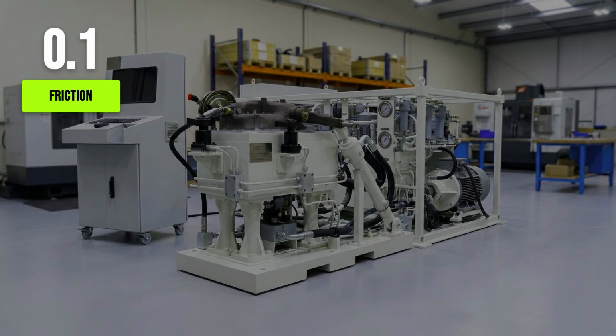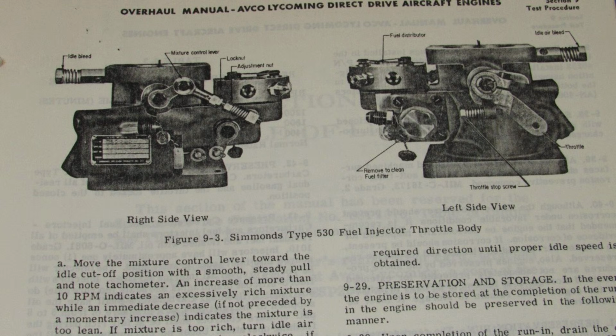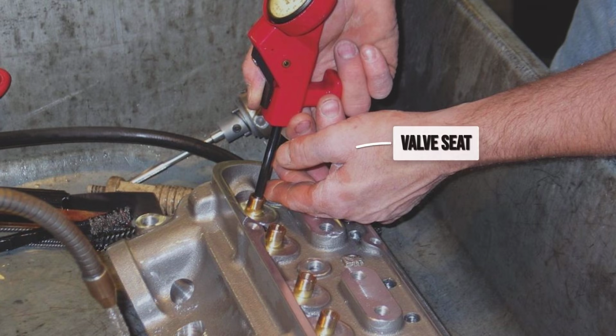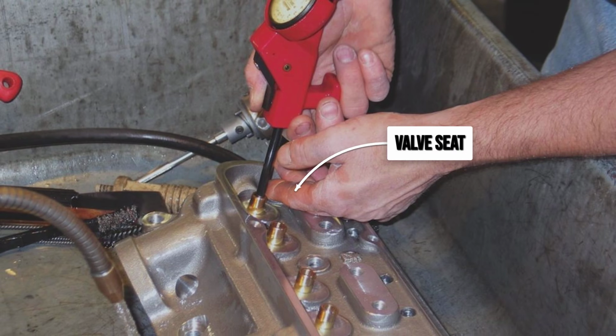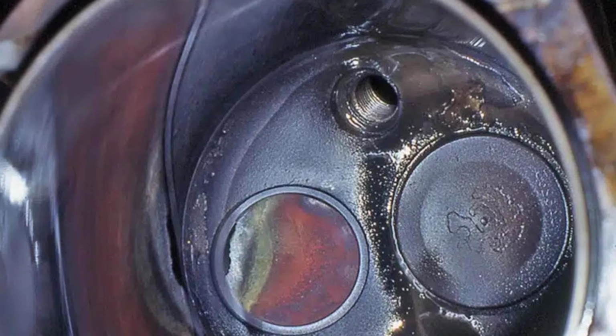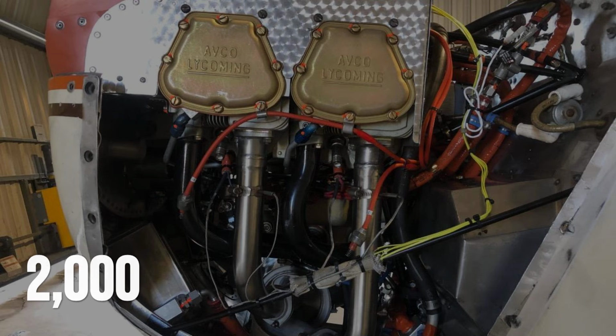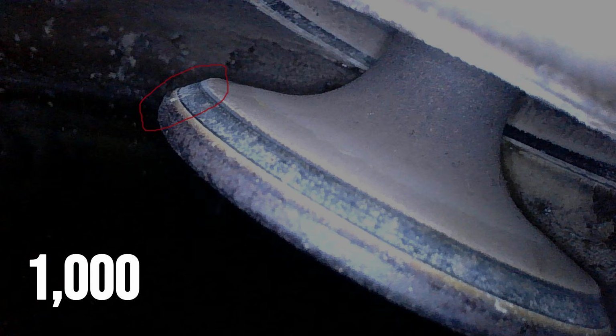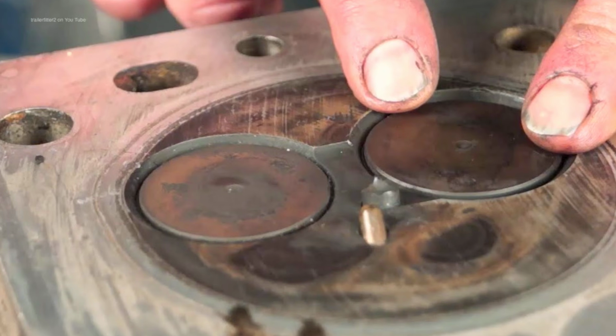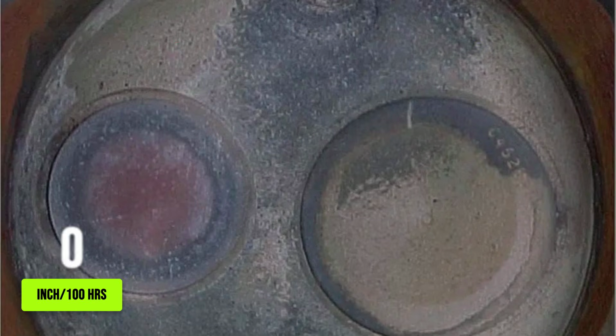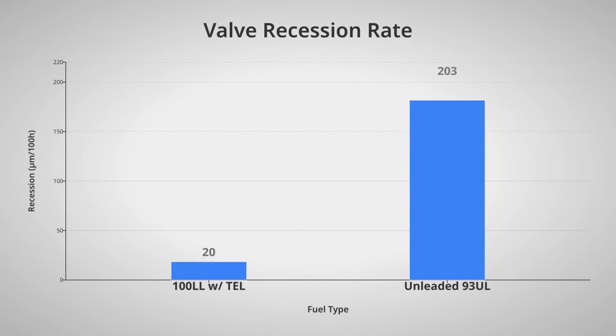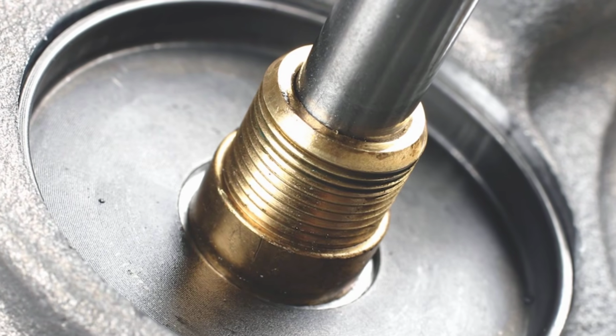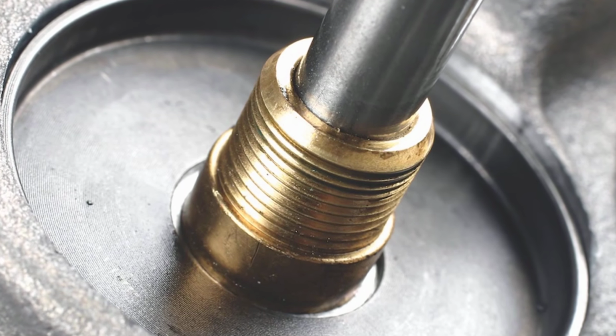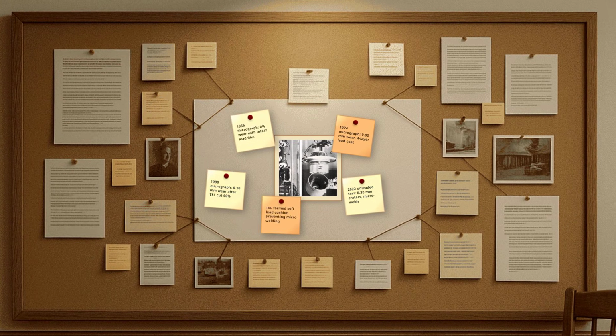Old service manuals from Lycoming and Continental spelled it out. Run unleaded, and you would see the seats recede, the valves burn, and the overhaul clock speed up. With lead, a 2,000-hour TBO was possible. Without it, you were lucky to see 1,000. Field tests in the 1950s measured recession rates at less than 1,000th of an inch per 100 hours on tetraethyl lead, 10 times better than unleaded. The lead film absorbed the stress, protected the soft seats, and prevented the micro-welding that destroys a valve face.